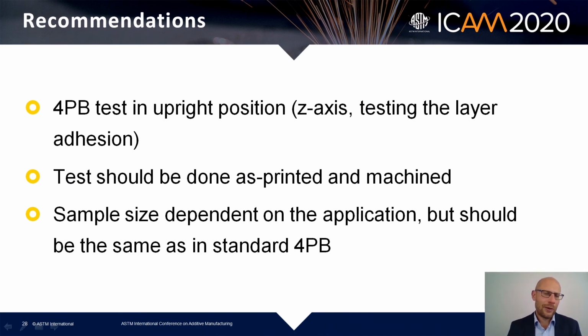So you build the part like this, and then you can test it like this, and then you really test the layer adhesion. We strongly prefer that the test should be done machined, this is possible, but also, and this is very important, it should be done as printed, because if you have the actual part, you will not be able to machine it everywhere and test it, and you will have a multi-axial tension, and then you have the as printed quality on your part. So we strongly recommend to also do as printed testing in order to really get the real values. And as we have seen, the difference is not so big. So as printed is for sure a method which should be taken very much into consideration, and should also come, in our opinion, into a standard.